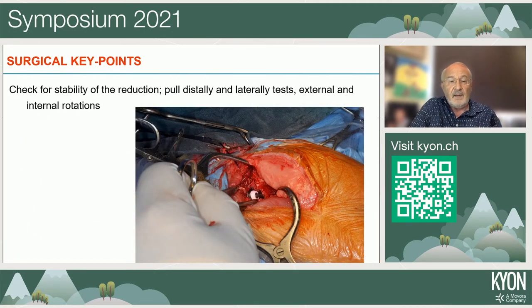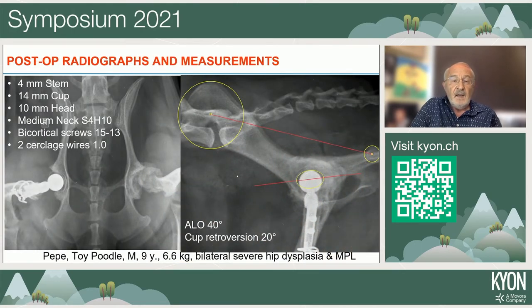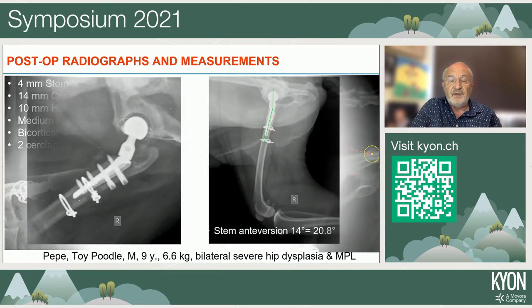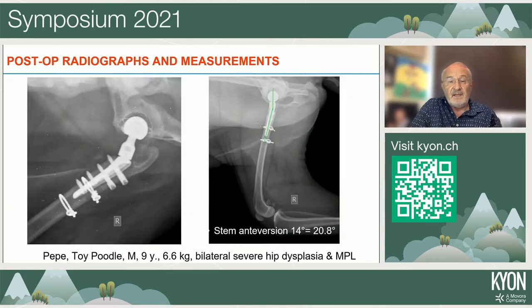Then we do our testing for stability as usual. We take our X-rays, very important to take consistent X-rays to be able to measure the angle of lateral opening and the cup retroversion, and also the stem anteversion in a proper mediolateral view with the stifle at 90 degrees.